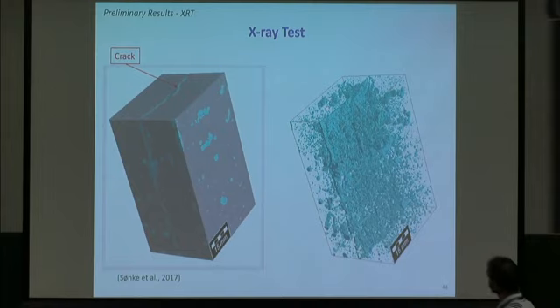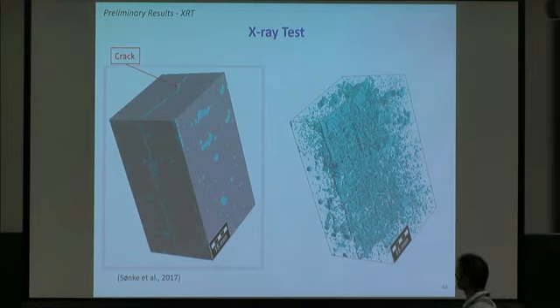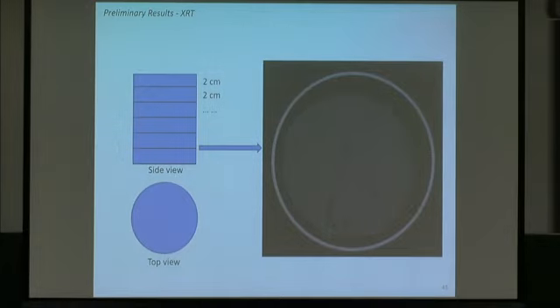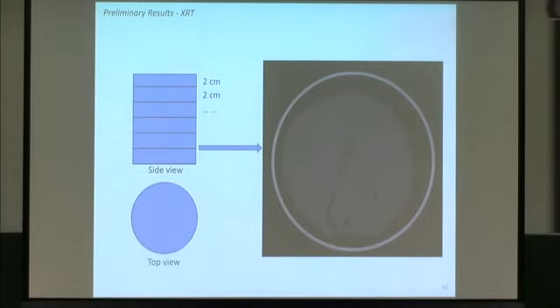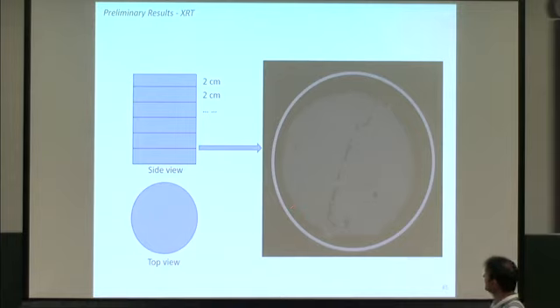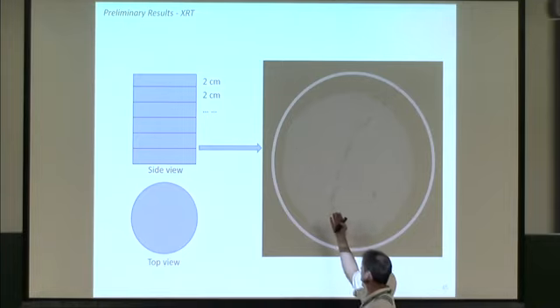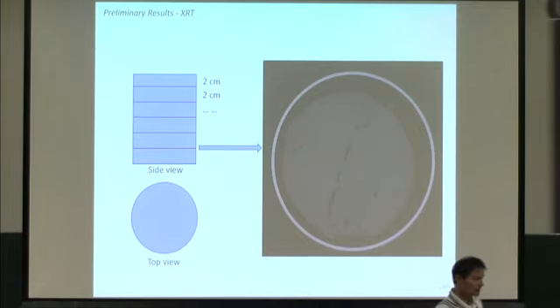What you can also see is that there are quite some inclusions here of brine pockets and air pockets as well. So there is a complicating factor. That's nothing to discuss. That's quite clear. If I now take this sample and take a layer, integrate over 2 by 2 centimeter down the way, you will see a video now where you can see that. So the video goes down from the top of the sample towards the bottom of that sample.